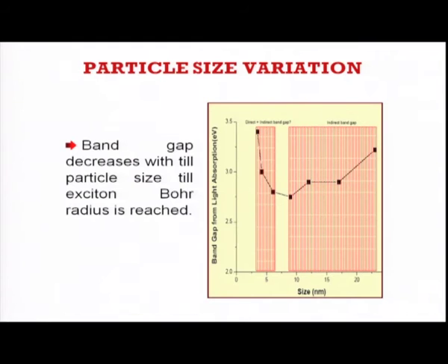And if you look at the size of the particle employed in this application, this is a diagram with the particle size range. This is the energy band gap. You can see here at this particular range where it is minimum, about 2.7. So, if you reduce the particle size to between about 5 to 8 nanometers, if you synthesize titanium dioxide particles in this range, it reduces the band gap, so that this nano-sized material can be used for direct solar light.